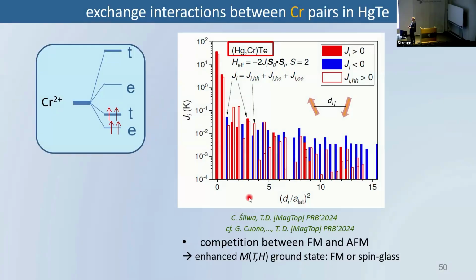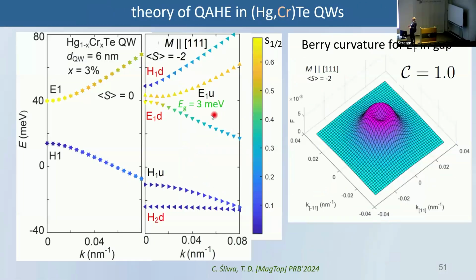And we found that the interaction between spins is, in many cases, ferromagnetic, which is good. We need spins to be organized in zero magnetic field. Here is the spin coupling as a function of distance between spins. Red means ferromagnetic interaction, blue antiferromagnetic interaction. And we also calculated what happens if the spins, chromium spins, are polarized. And we found that for a certain orientation of magnetization, we have a gap, and this corresponds to a situation that in one channel you have an inverted situation and in another channel a not inverted situation. We also calculated Berry curvature and found that the Berry phase or Chern number is not zero, so we expect this quantized value.